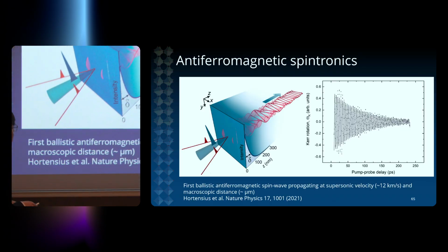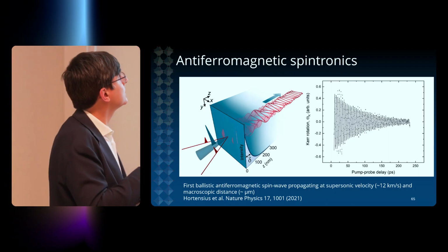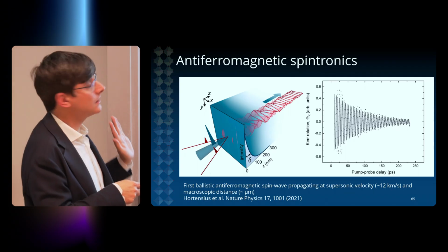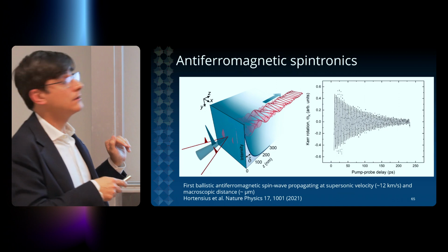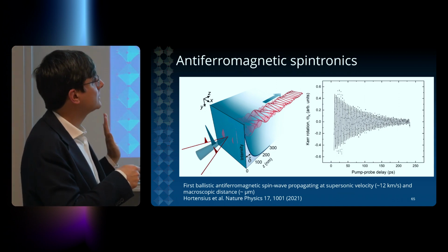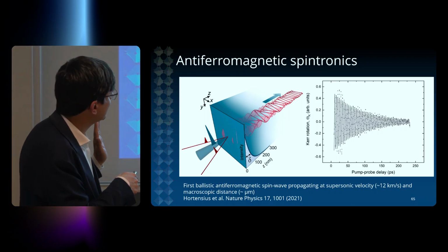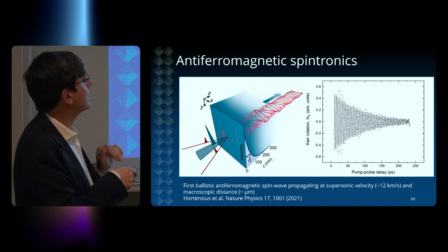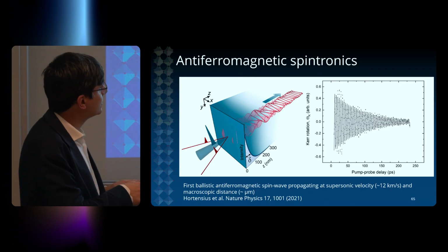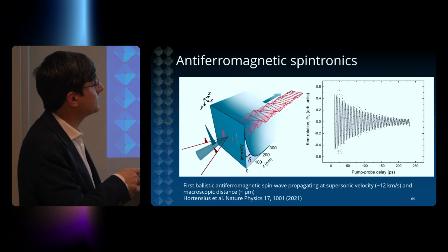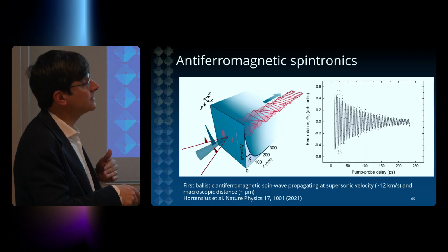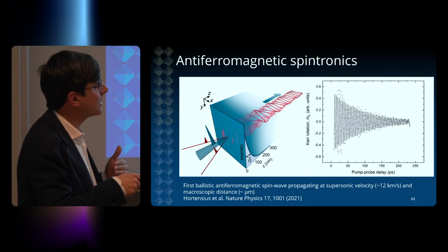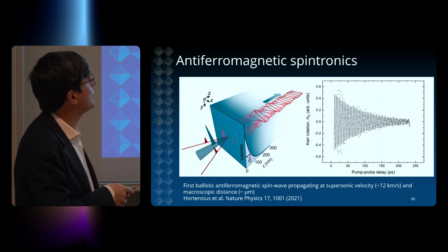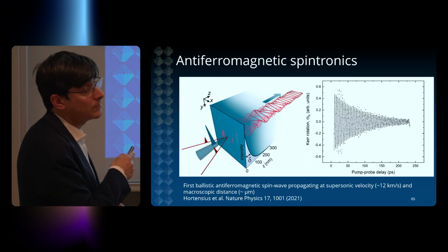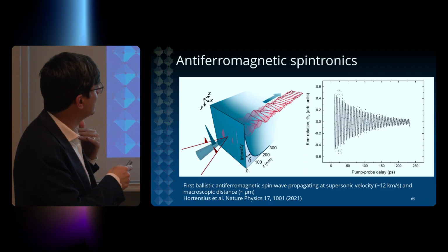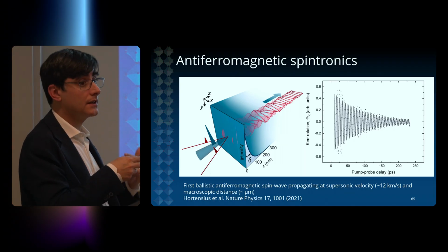The other example that I wanted to give you for light control of materials is the generation of spin waves. So in the same material, again, by using laser pulses, we were able to induce for the first time ballistic antiferromagnetic spin waves propagating at supersonic velocities. So this is by impinging on the material a certain laser light that was exciting a very narrow region of the surface of the material and the spins of the material. We could induce oscillations of the spins that would propagate inside the material over macroscopic distances, on the order of microns, with a ballistic character. So this is a coherent propagation of angular momentum, which is important for an emerging field called antiferromagnetic spintronics. And again, this is made possible by having this specialized surface that has specific interaction with light.